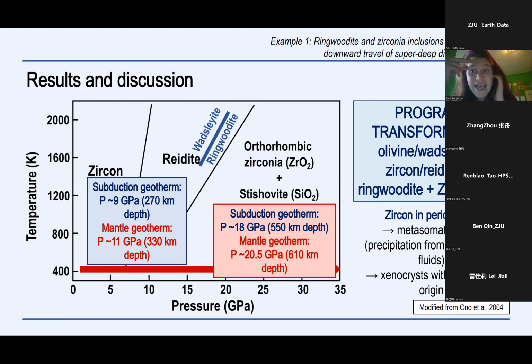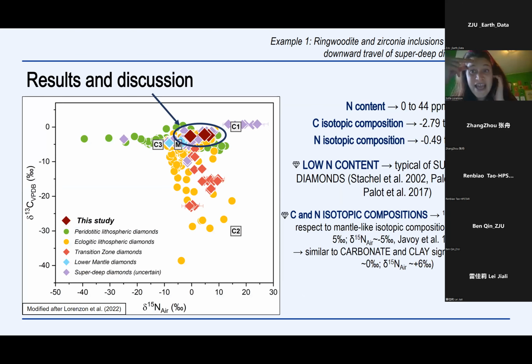So continuing with the data that we obtained from the secondary ion mass spectrometry, we found that our diamond has a low nitrogen content, a quite negative carbon isotopic composition, and a quite positive nitrogen isotopic composition. And okay, what does this mean?